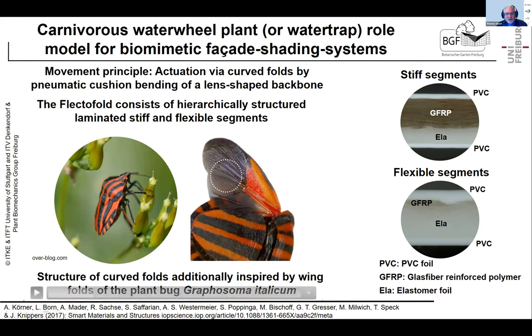If you look at the hind wings here, for example, of an Italian bug, the Graphosoma italicum, they fold and unfold the hind wings several thousand times in their lifetime, and you never see a failure in the hind wings. And if you look here, then you see that these kind of folds are specially built. They have a kind of bulging structure, which is slightly omega shaped, and including this in our flectofold, we could reach opening cycles up to 10, 15, 20,000 times.